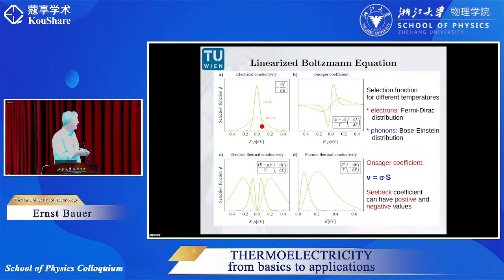What does it mean? It means if 0 points out the Fermi energy of the material, and if we increase the Fermi energy a little bit, or rather the chemical potential, or if we decrease it a little bit, then different parts of this electronic structure in the vicinity of the Fermi energy are going to contribute to this charge carrier density. And clearly there's a difference for this derivative, whether we have, for example, 300 Kelvin or 1000 Kelvin.